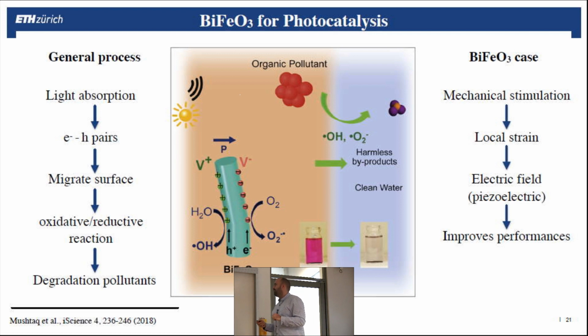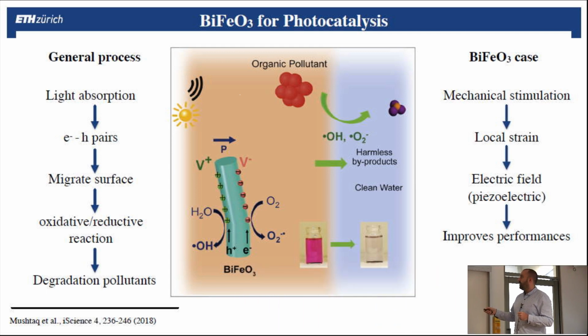Let me go to now a more fun example, a little bit out of material science, but it has been shown that bismuth ferrite can be used for cleaning water. So imagine that you have an organic pollutant in your water, and you have bismuth ferrite, or a part of this material, in your solution. What is known is what is here. Generally, what people do to clean water from this organic pollutant is by applying light to the material. This material will absorb the light, and this energy will create electron-hole pairs that will migrate to the surface of the material. By doing that, they will start oxidative or reductive reactions, and this will result in degradation of the pollutant. But what they observed is that if they put here bismuth ferrite,